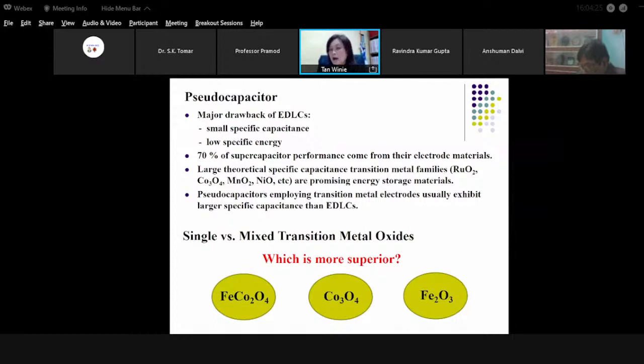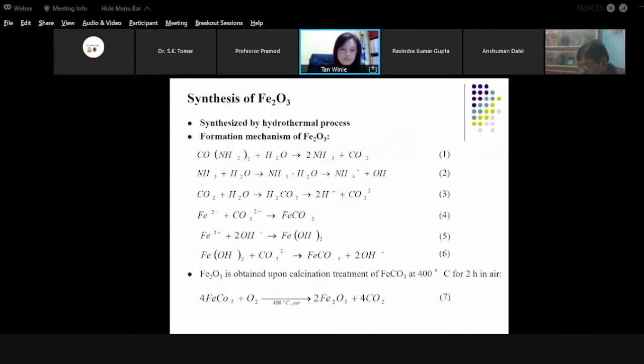So this is what I'm going to share with you, some results from our laboratories on transition metal oxide based electrode materials. We have iron cobaltite and also single metal oxides, which are iron oxide and cobalt oxide. We synthesized them using the hydrothermal process. Why did we choose the hydrothermal process? Because it has low synthesis parameters, it's cheap, and gives good oxygen stoichiometry.